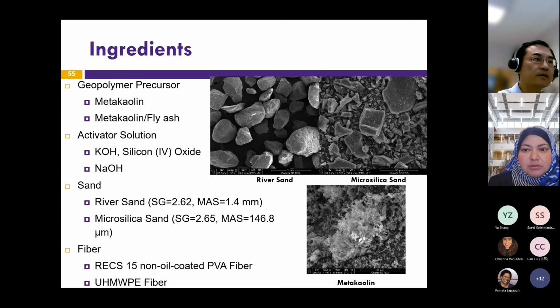Okay. So this slide shows the ingredients that we experimented with from a geopolymer precursor perspective. As I said, we tested metakaolin and a hybrid metakaolin fly ash combination. From an activator solution perspective, we tested potassium hydroxide with silicon dioxide and sodium hydroxide. And then we experimented with river sand and microsilica sand. And then for fibers, we had non-oil coated PVA fibers and ultra-high molecular weight polyethylene fiber.